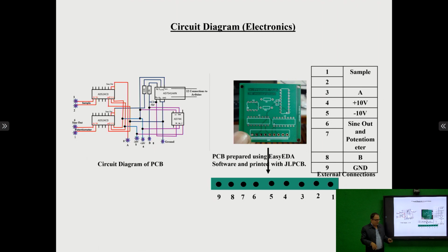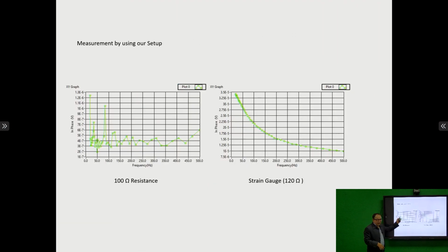We ordered it, received it, and made the whole setup in our lab. We performed the measurement with a 100 ohm resistance, and in the 100 ohm resistance you see there is only fluctuation. But with a strain gauge, which is a thin film heater, you get the 3 omega signal very easily from that setup. This is the setup we have recently made in our lab.